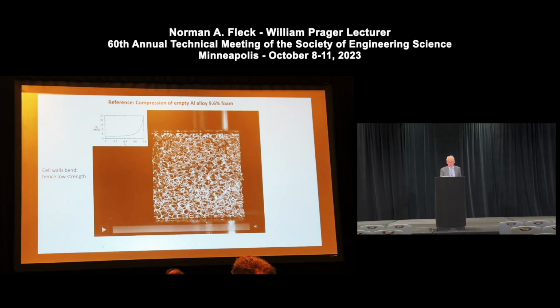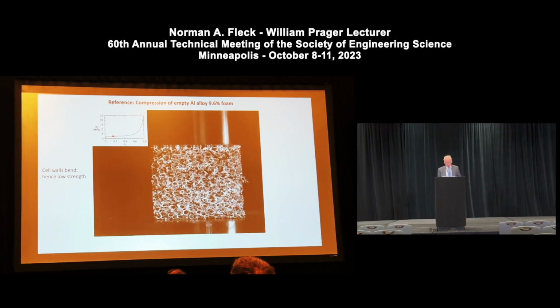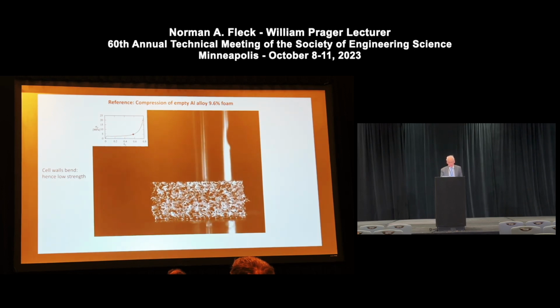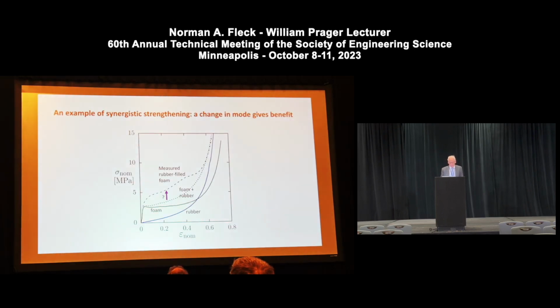And for reference, as we've seen before, if we don't have an incompressible phase added, then we see a softening response with formation of various crush bands, instabilities. If I plot the stress strain curve and compare them for the open cell foam, it's here, plateau-like behavior associated with formation of crush bands, whereas if I add the rubber to the foam, the measured response goes up to the dashed line. So there's a significant enhancement in properties and, as I said, a stabilization in behavior. Just for reference, the rubber alone would deform in this way and by the blue line, and if we add the rubber response crudely by rule of mixtures to that of the open cell foam, this would be the result. So we have got a synergistic effect, essentially by changing the deformation mode of the lattice.